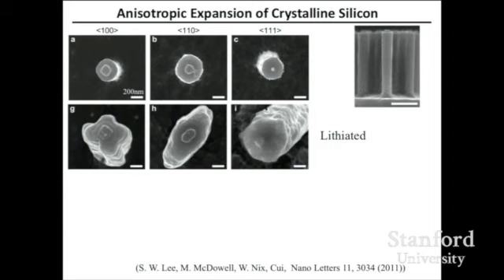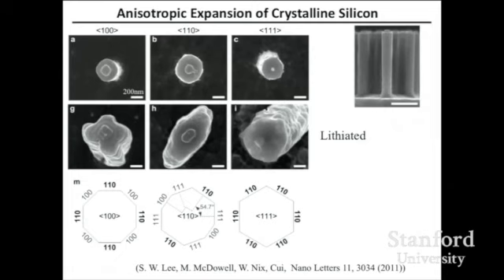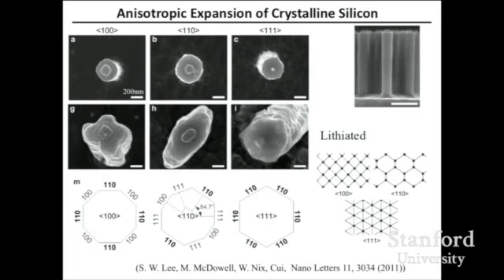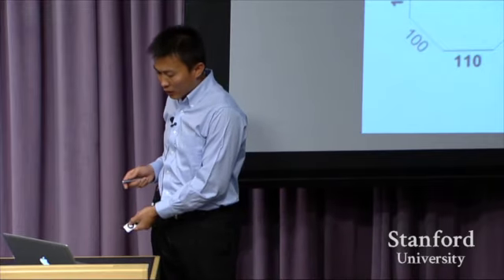Thus, the expansion is highly anisotropic. This has implications in your battery design. If you put silicon together, depending on the orientation of the crystal structure, the expansion in different directions is different. So you need to think about that when designing your battery electrode. And it turned out this expansion all happens along the 1, 1, 0 direction. This has 4, so it has 4 directions. This has 2 right here, the sidewall. And 110 is quite unique. 110 has a crystal structure with open channels ready to react with lithium. It goes very fast. That's the expansion direction. This was nicely done in collaboration with Professor Bill Nix right here at Stanford University, a local mechanical expert who helped us figure out a lot of this expansion phenomenon.